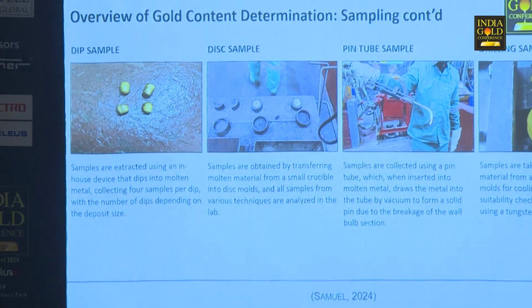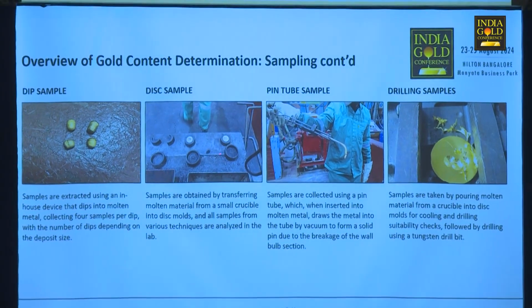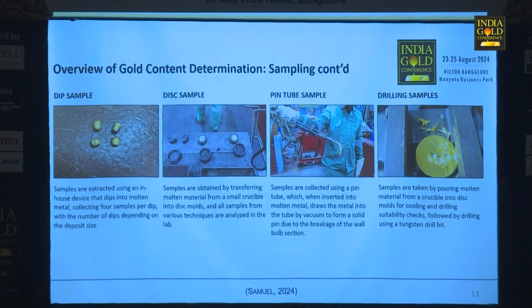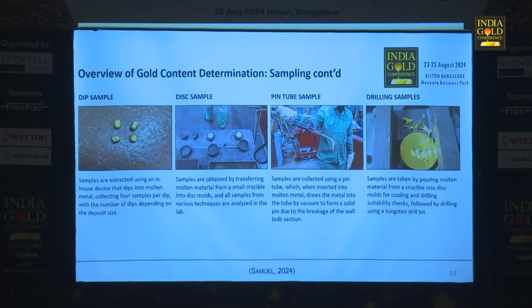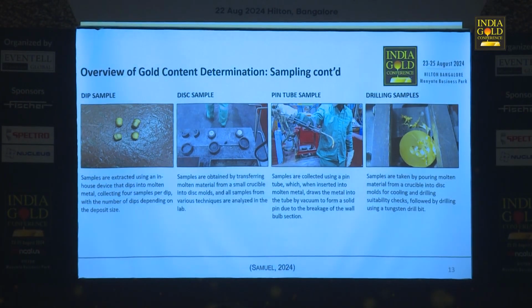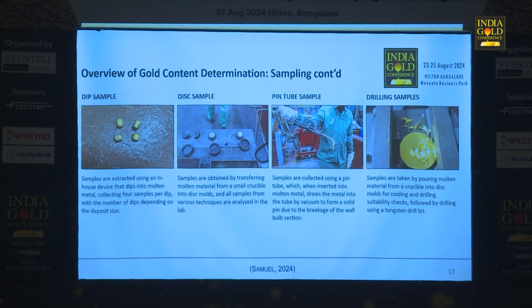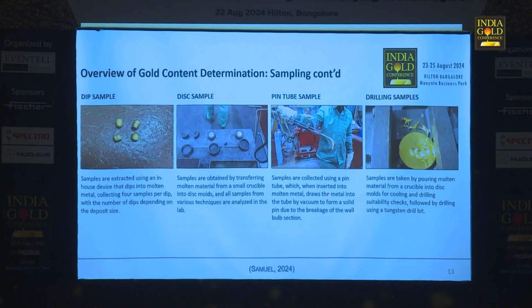So these are some of the samples that we do take. The dips, as I said, we're taking 8, but at the lab, on average, we analyze about 5, which are randomly selected on a small deposit. But if the deposit is higher, obviously the number of samples that we take is higher. And then these are the samples that, as I said earlier, we take 2 and we analyze them in our 2 XRF machines. And then we've got quality parameters to make sure that when the results come out, we compare the 2 results as well to make sure that they are in sync. And then we've got an ability to take pin tube and also the drill samples.